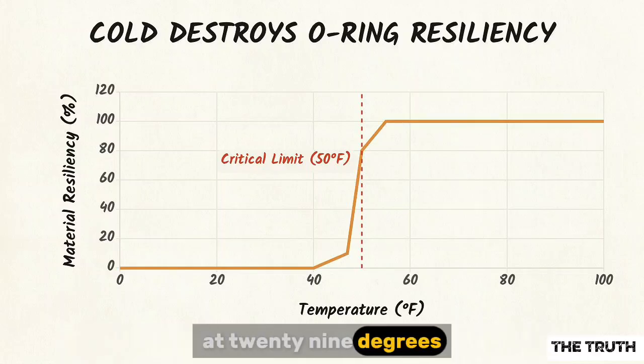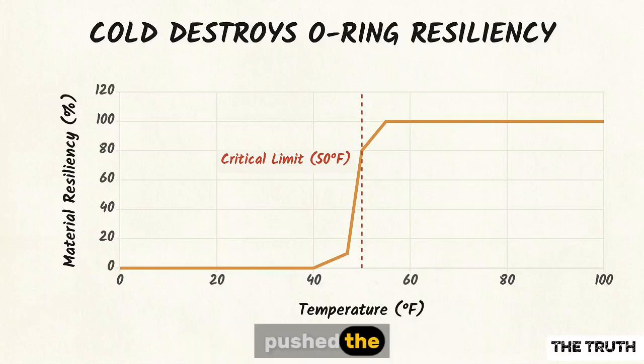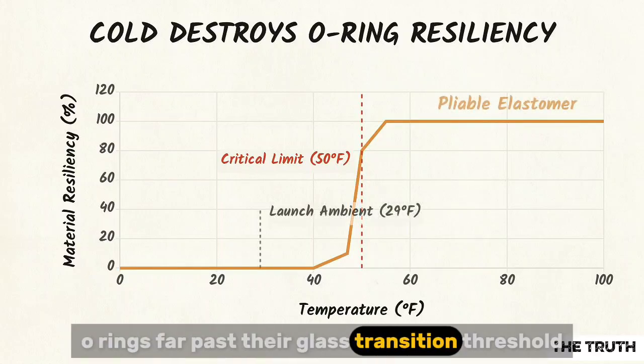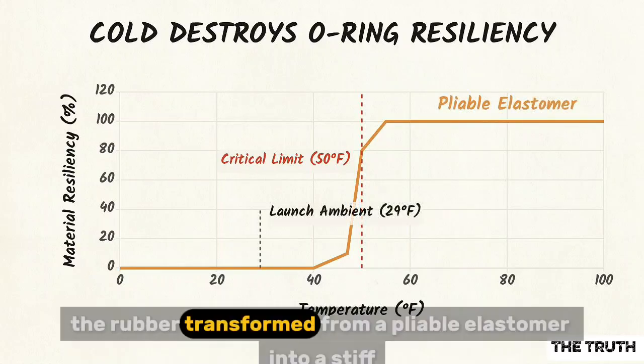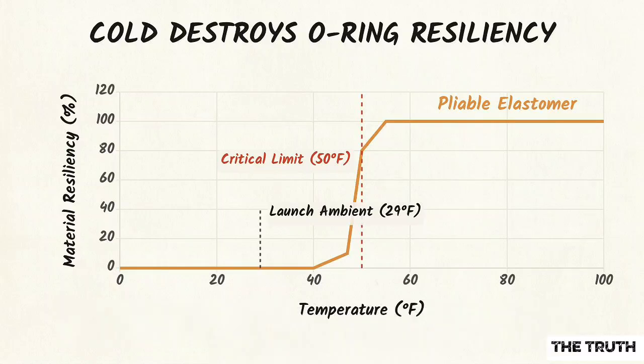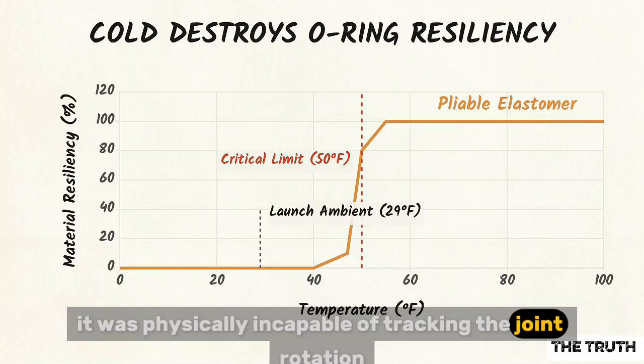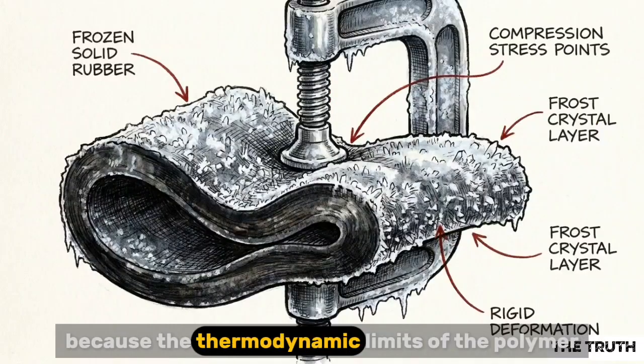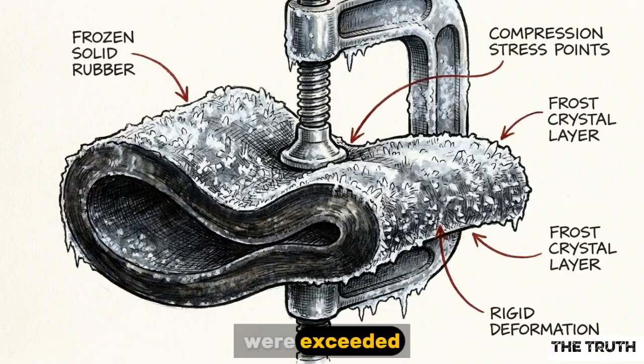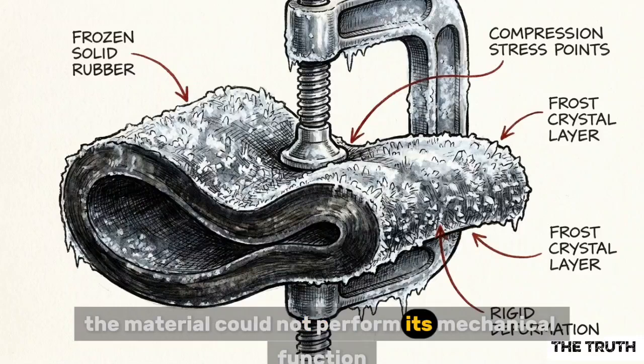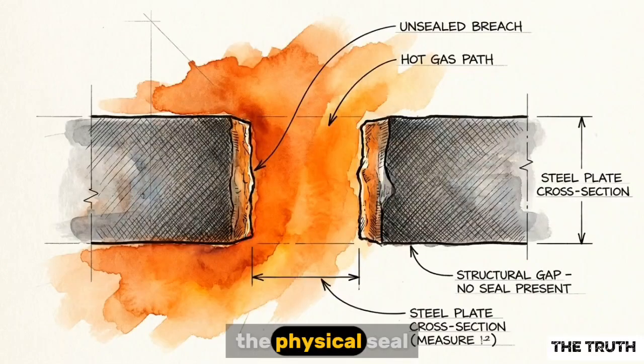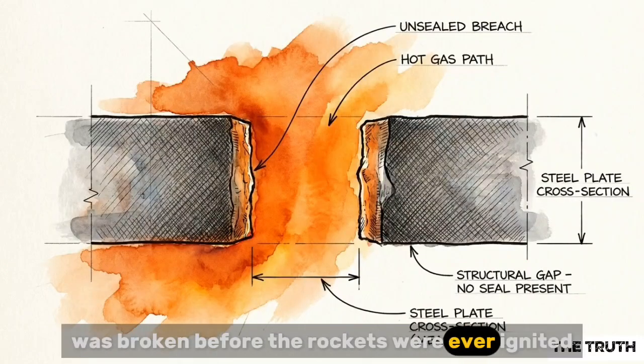At 29 degrees, the freezing ambient air pushed the O-rings far past their glass transition threshold. The rubber transformed from a pliable elastomer into a stiff, brittle, glassy state. It was physically incapable of tracking the joint rotation. Because the thermodynamic limits of the polymer were exceeded, the material could not perform its mechanical function. The physical seal was broken before the rockets were ever ignited.